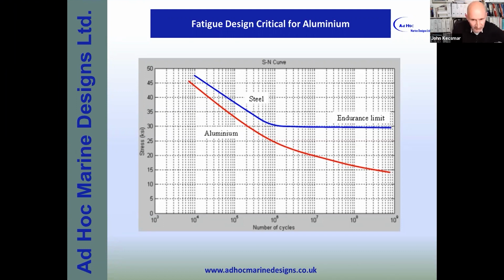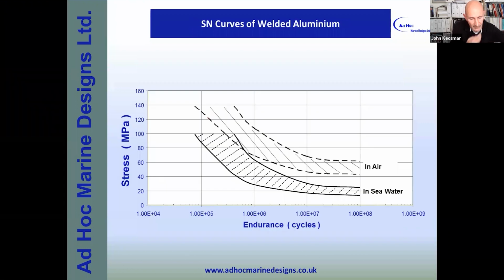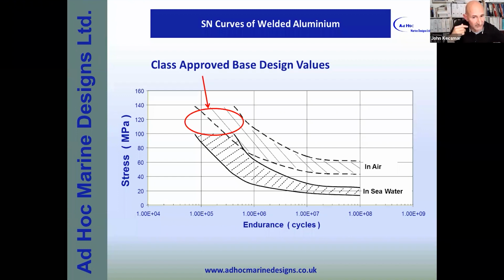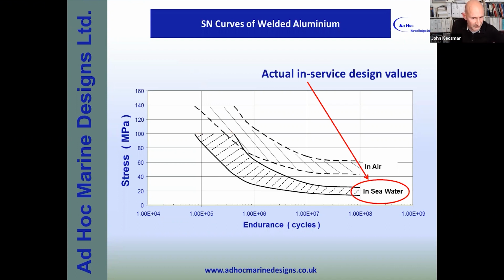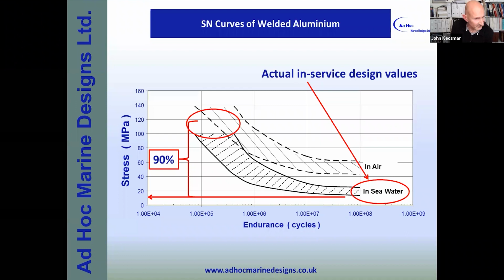So when I was a young graduate, I was thinking, gosh, well, what do I design to? And I did some research, and I was tasked with designing the water jet ducts of some of our vessels. And I found this, at the time, unpublished US Naval research, and they did some very simple tests of welding 5083 aluminium. And you can see here that the class approved base values are, as you'd expect, around 120, 125 MPa. Whereas once they're subjected to an environment like seawater, there's a significant reduction in the amount of allowable stress, by anything up to 90%. So I took this on board and decided to design my water jet duct to this very limit of 10-20 MPa.